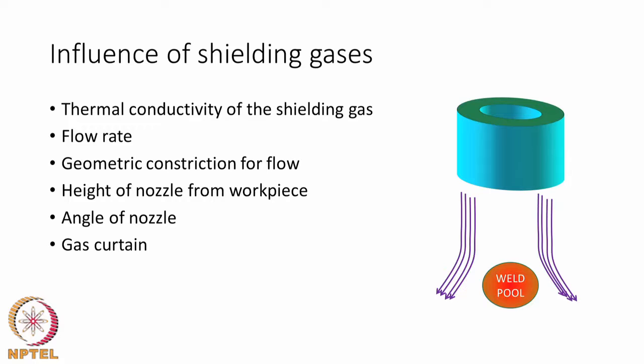The angle of the nozzle also plays a role. It may induce asymmetry in the heat source distribution. If the welding torch along with the gas nozzle is kept perfectly at 90 degrees to the workpiece, then symmetry is expected in the heat source distribution. But if it is at an angle, then you may not have that symmetry, if the shielding gas is going to play a role in significantly altering the heat source.